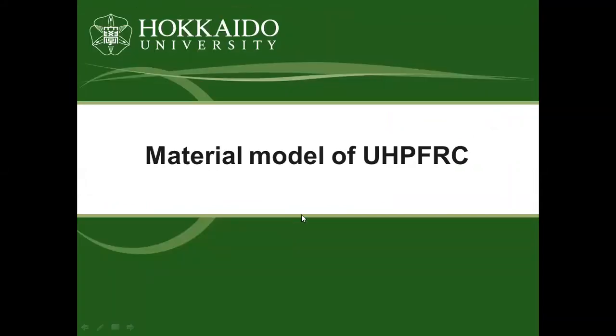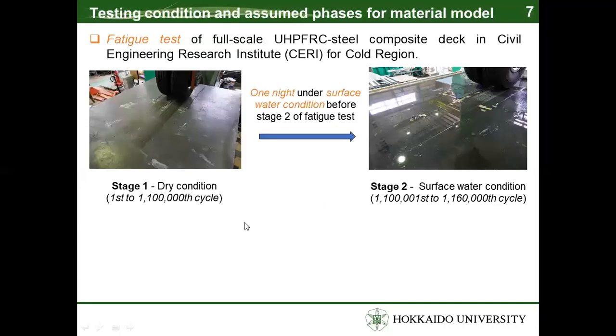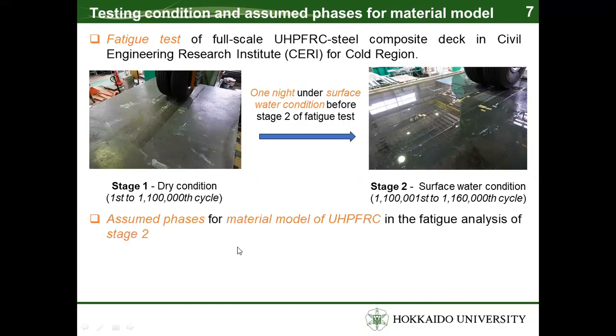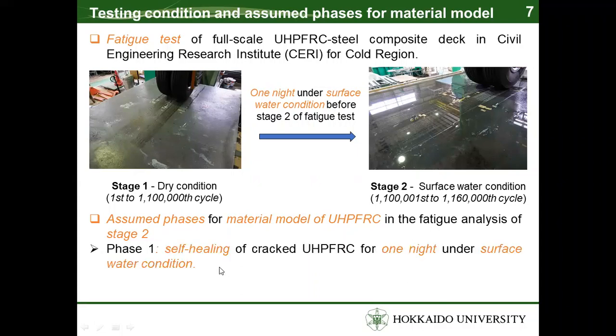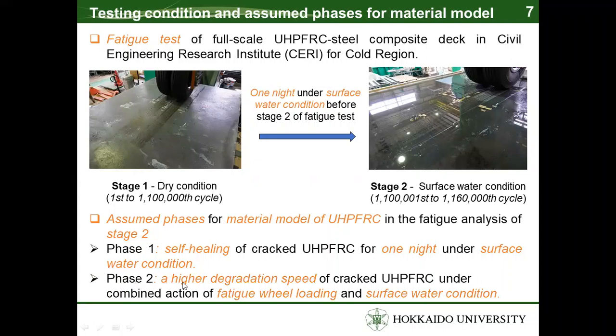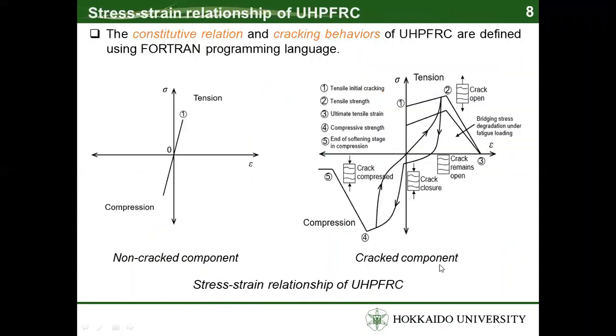Material model of UHPFRC. After the first day under dry conditions, water has been supplied on the top surface of the overlay for one night before stage 2 of the fatigue test. Two phases for the material model of UHPFRC in the fatigue analysis of stage 2. Phase 1, self-healing of UHPFRC for one night under surface water conditions. Phase 2, a higher degradation speed of UHPFRC under combined actions of fatigue wheel loading and surface water conditions.